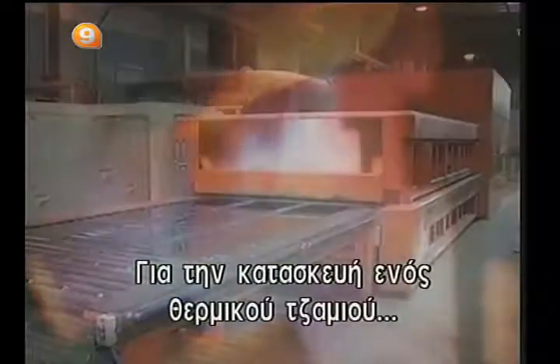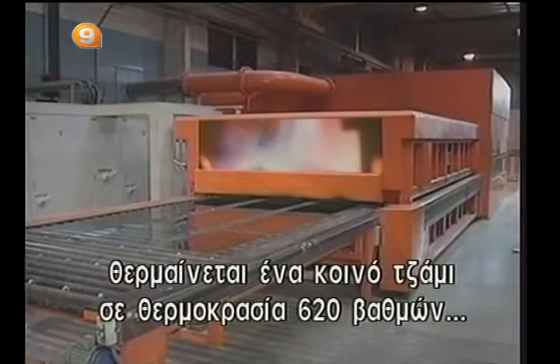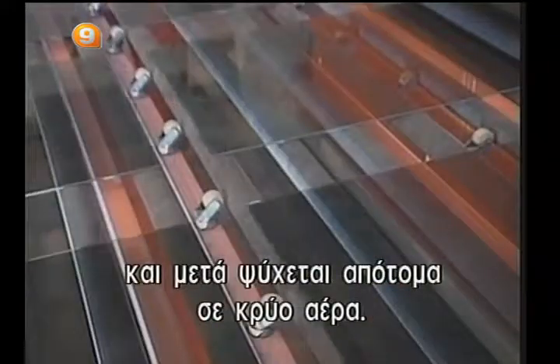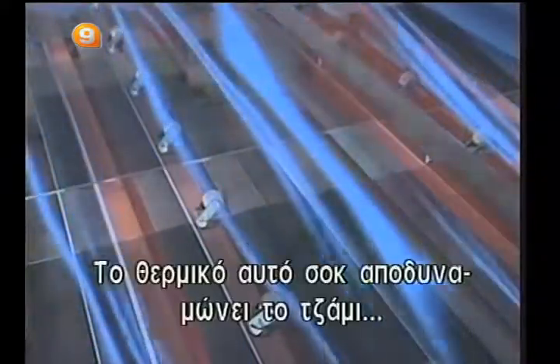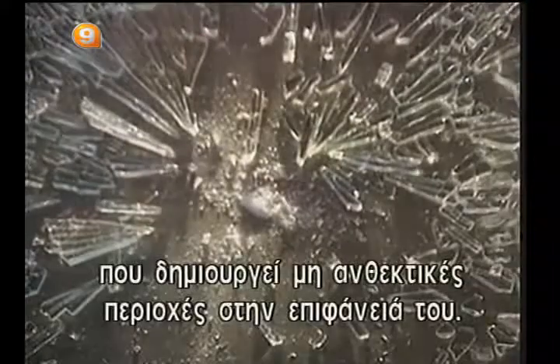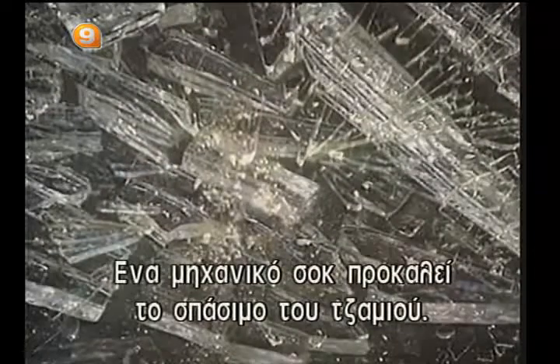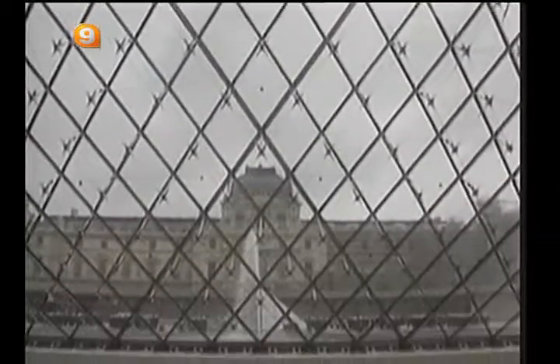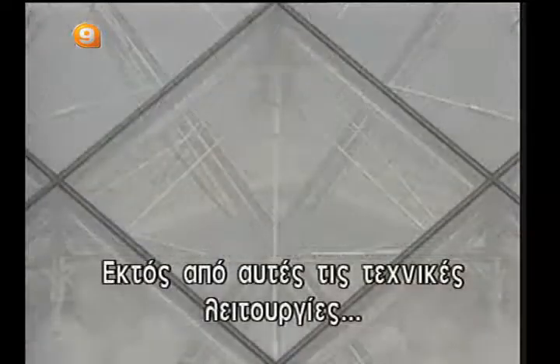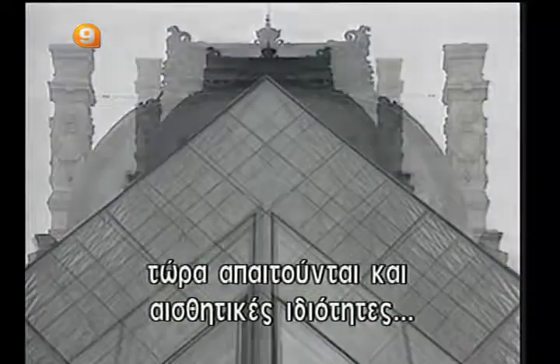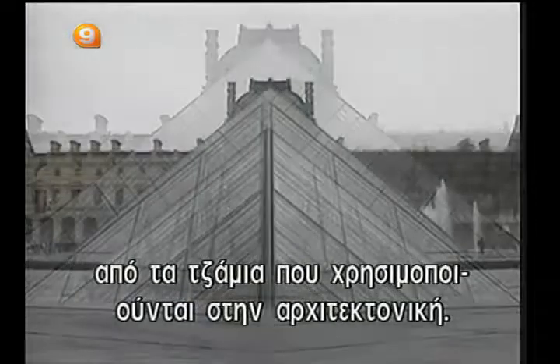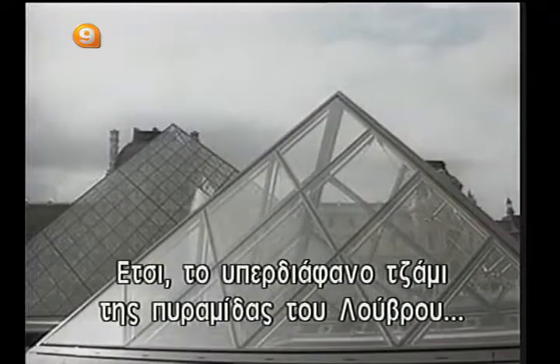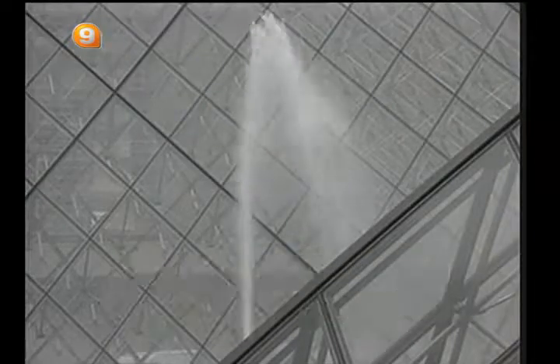To make tempered glass, a conventional sheet of glass is heated to 620 degrees Celsius and abruptly cooled in cold air. The resulting thermal shock weakens the glass, creating numerous less resistant areas over its entire surface. A mechanic shock will cause the glass to shatter all over. In addition to these technical functions, we now require that the glass used in modern architecture have aesthetic qualities. In this regard, the ultra-clear glass over the Pyramid of the Louvre in Paris is quite a technological feat.